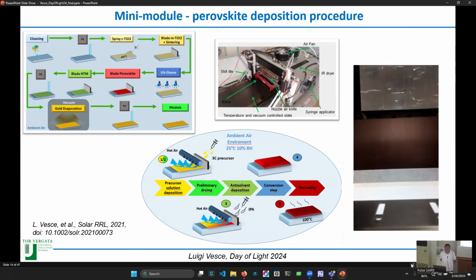As you can see from the picture on the upper left, the full process is in ambient air. Generally one prefers to work with perovskite in a glove box with a nitrogen environment, but here we work in ambient air. The ambient is controlled with the fume hood and so on, but we have oxygen and some moisture, controlled in some way to about 30–40% humidity, sometimes less. But we are not in the glove box, so it's more similar to a process manufacturing.